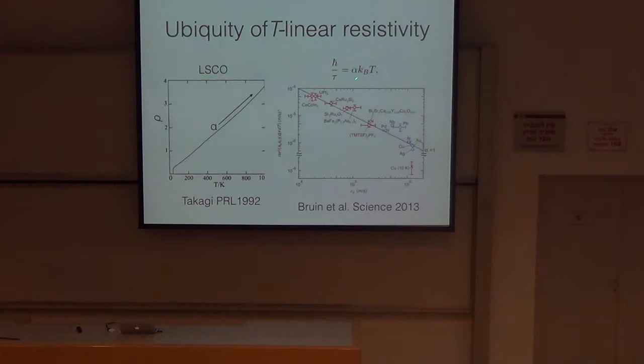And they figured out what this prefactor alpha is. Now, some of you in this room might already be familiar with what that value might be, but it turns out that for a number of different systems, that number is 1. In other words, there seems to be, on average, an exact equivalence, within a factor of 2 or 3 it turns out, but a pretty close equivalence of the energy scale associated with the scattering rate itself and the energy scale of temperature. And this is a highly non-trivial effect.